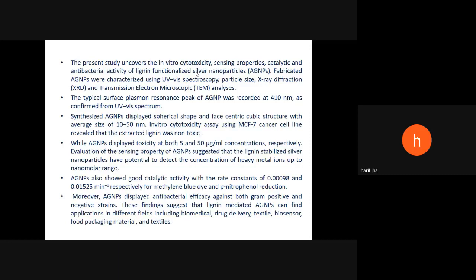So these lignin functionalized nanoparticles were used for detection of a specific metal ion. How exactly does detection take place? As you know that nanomaterial, due to the quantum effect, their surface and charge ratio, or electron ratio, deviates from a normal macromolecule or micromolecule. And due to that deviation, they have changes in color and texture. And when the binding of a metal ion with this silver nanoparticle takes place, this again changes.